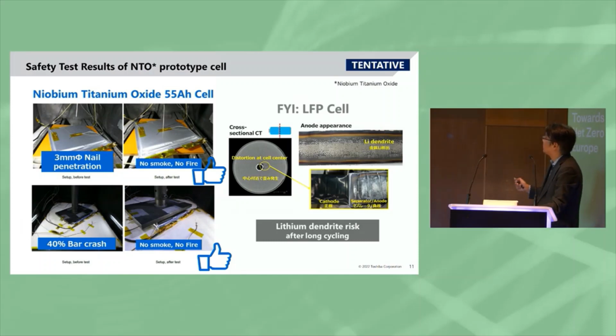This is just information from our experience. LFP is also a safe battery in general, but at the end of life, we can see a lot of lithium dendrite on the anode in this case. This is maybe generated by the charging situation, and sometimes it becomes a trigger of internal short circuit and thermal runaway. So the charging condition of the LFP battery will be limited carefully. And the NTO battery doesn't have these mechanisms of lithium deposition. So we think this high level of safety will be maintained through the end of the battery life.